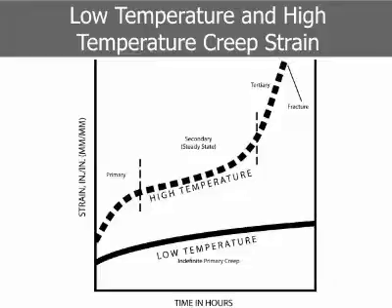The actual shape is determined by material, alloy variations, stress level, and temperature. Primary and secondary creep are generally considered in design. Total creep decreases rapidly with reduced stress levels. In one alloy, a 50% reduction in stress reduces creep deformation by 90%. The low temperature curve describes aluminum and magnesium alloys at room temperature.